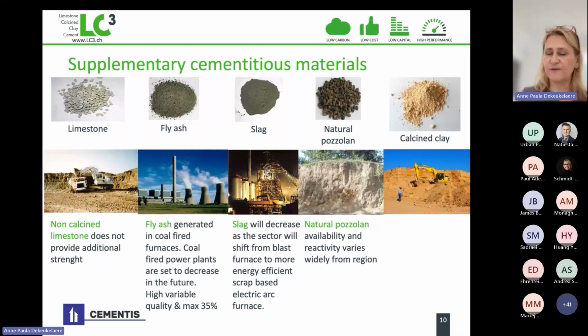Then we had also slag. Slag was, and still is, a very good cementitious material. It's a waste from the blast furnace. The issue is that the volume on Earth is already used. We expect the overall volume of slag to reduce because the steel industry will go from blast furnace to electric arc furnaces. So that will reduce the slag. We also have natural puzzolana, which some are reactive, some are not reactive, but it varies widely from region to region. So there we don't have the availability of this resource everywhere in the world. It depends. And then we have calcined clay. We looked at calcined clay as a resource that is available worldwide in huge quantities.